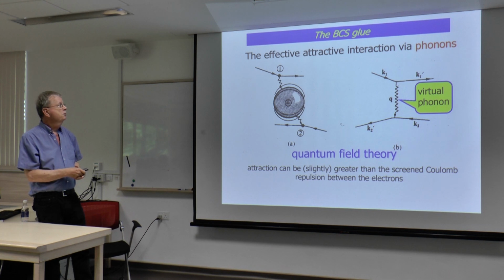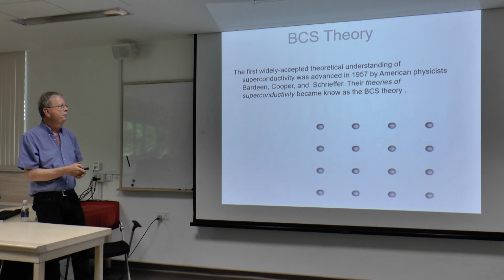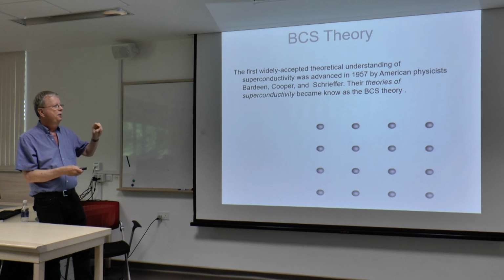So here we have an electron moving through space in K-space, and we have some virtual phonon being exchanged between them. We have a net effective interaction, and the point about this interaction is it's a retarded interaction in time. This cartoon is not terribly correct, but it will hypnotize you into thinking it's useful. One electron goes through and distorts the lattice. Another electron goes through and sees the influence of the electron that already left the area and took its giant 1 eV Coulomb repulsion with it. Because remember, the attractive interaction between these paired electrons is the order of milli-electron volts. So if the Coulomb repulsion from the first electron is still around, you're not going to get a net attractive interaction.